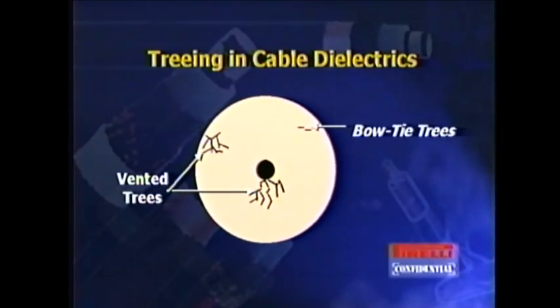The ones we really have to watch out for, though, are vented trees. And vented trees usually start at the conductor shield or the insulation shield interface and are usually caused by water migrating into the insulation system. That, with the combination of voltage stress, again, will cause a degradation of the insulation, which, as you degrade the insulation over that time, you really have kind of like a hairline crack, and you have a very high stress. As the tree grows, you increase the stress more and more, and you usually increase it to points where the insulating material can't stand that high of a stress and it breaks down or fails. So long story short, you want to try and keep trees from growing within the insulating material.